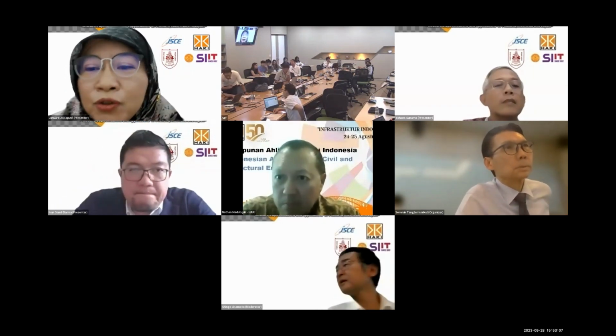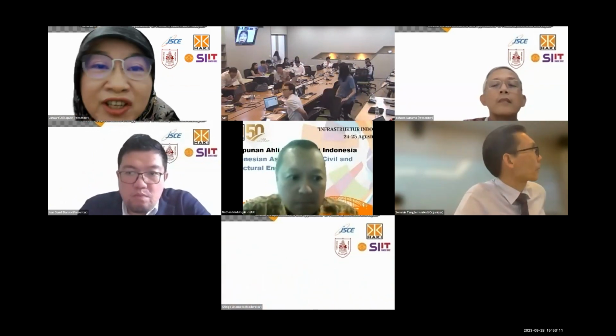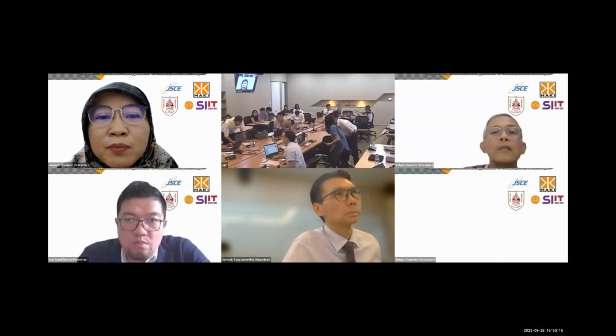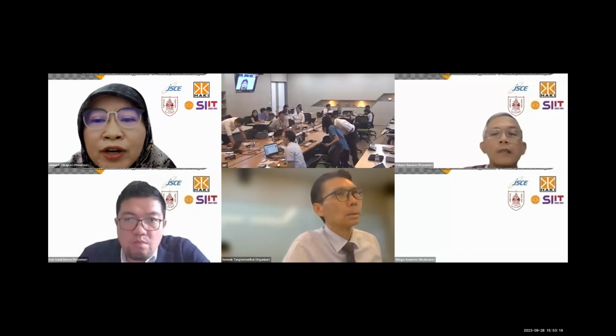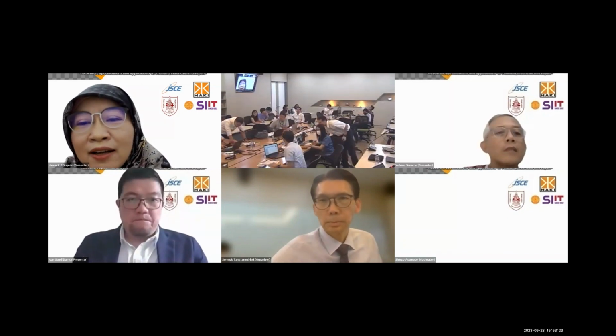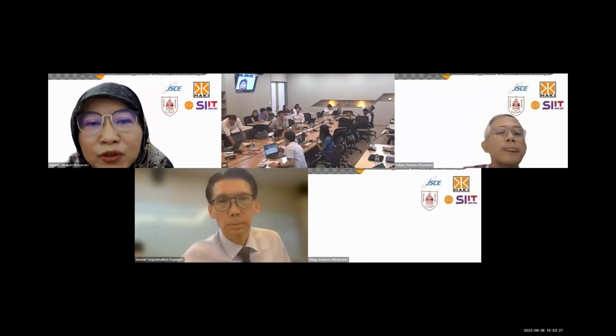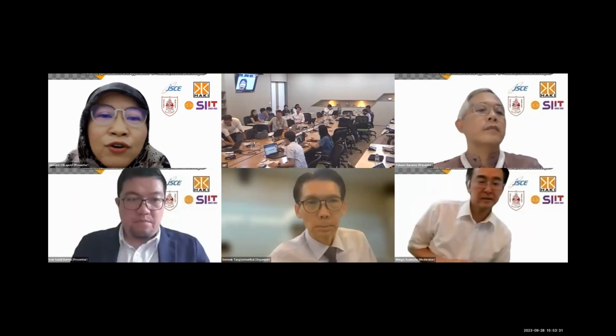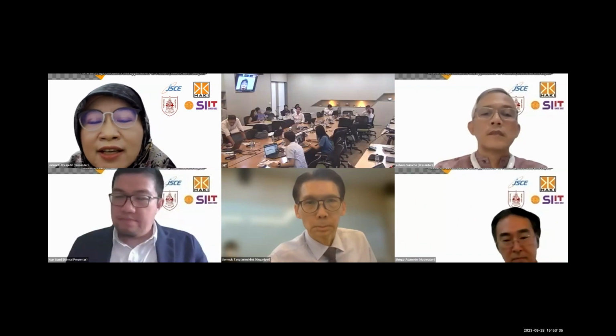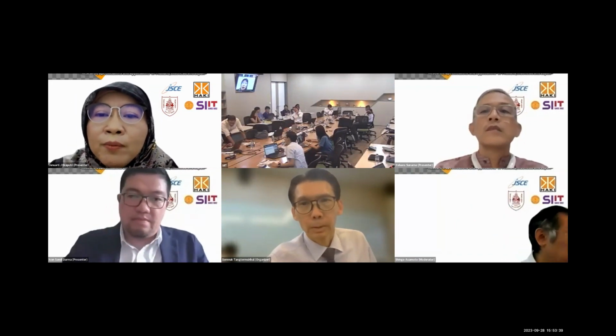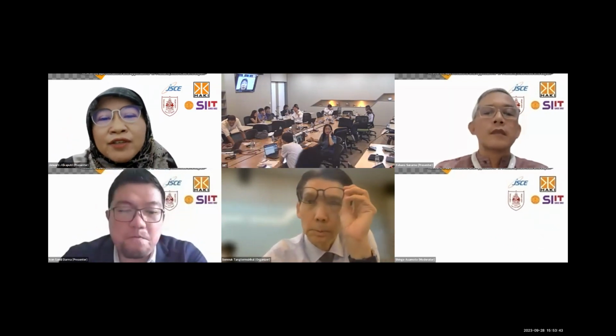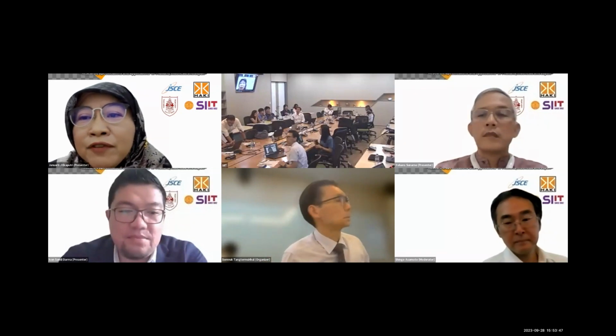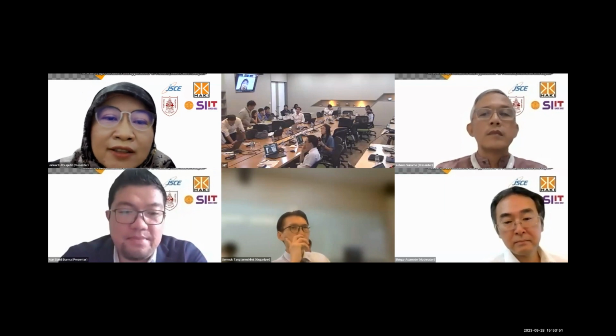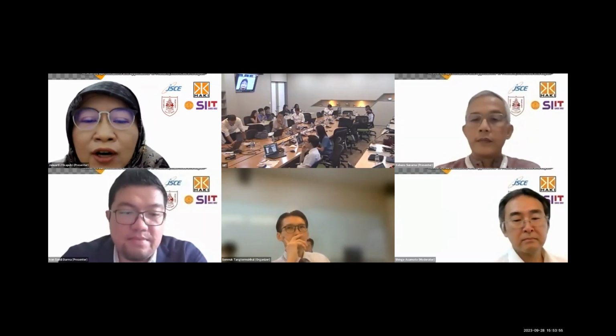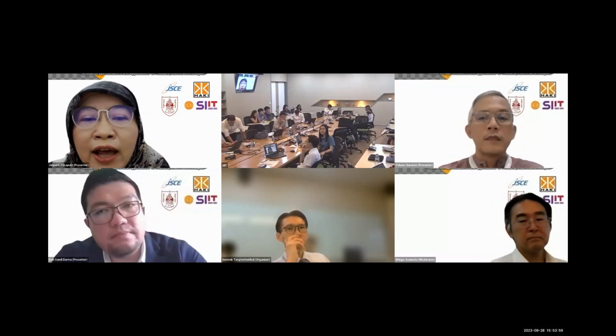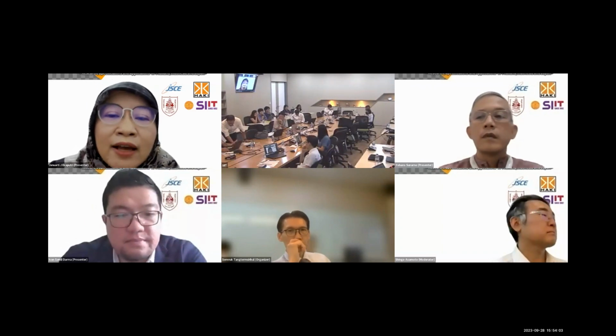Yes, thank you very much. I will try to answer the question. Recently, we understand that carbonation becomes a great issue for concrete. However, as already explained by Dr. Warangkana, we can use fly ash, even class F or class C, to replace cement against carbonation. Actually, carbonation is a problem when the porosity of the concrete is big. If we have a silica source, for example reactive silica contributed by class F or class C fly ash, actually we don't have to worry about that